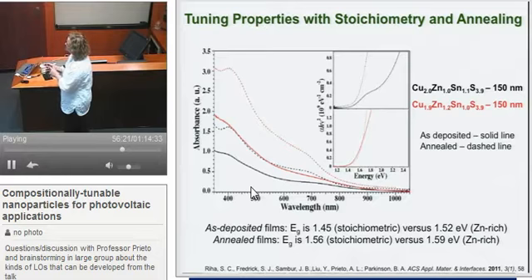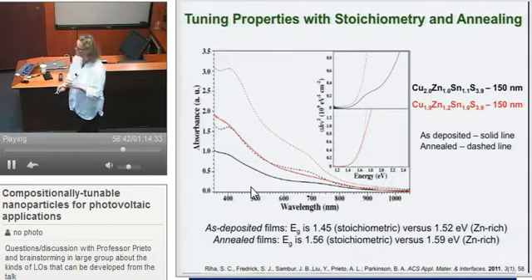Again, absorbance is a function of wavelength. The black here is the UV-vis that I just showed you. The red here is the copper deficient sample, and already you can see that it's absorbing more light. The particles were the same size, the same standard deviation, same size distribution, and the films were the same thickness. So the only difference was the composition.